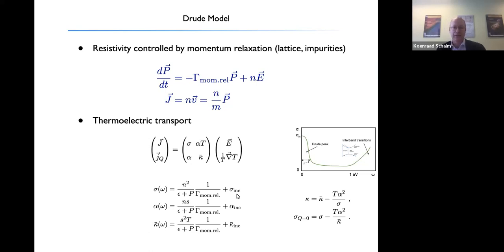These intrinsic, or incoherent, contributions are important in the remainder, and you can try to separate them out from the three types of measurements that you can do. You can measure the electric conductivity, you can measure the thermoelectric response, in other words, what happens to the heat current in the presence of an electric field, or what happens to the electric current in the presence of a temperature gradient. And this is the heat conductivity in the system. You can extract this incoherent piece by looking at the heat conductivity in the absence of a charge current, or the charge current in the absence of a heat current. They are given by these two combinations here. So this separates out these incoherent contributions.